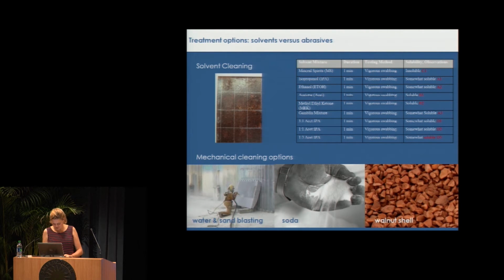So the 6 main challenges for this treatment were how to remove different layers of coating that we don't really know what they are in one technique. And indeed, as Julie said, it's kind of impossible, but I wanted to try it anyway. Have a treatment that was gentle enough to keep most of the iron corrosion, because as you know, iron is really hard, but the corrosion on top of it can be very fluffy and loose. So you have this tricky thing that you have this hard metal, and then you have this porous, loose corrosion that is penetrated with this horrible coating. So it was kind of difficult to find a good treatment for that.